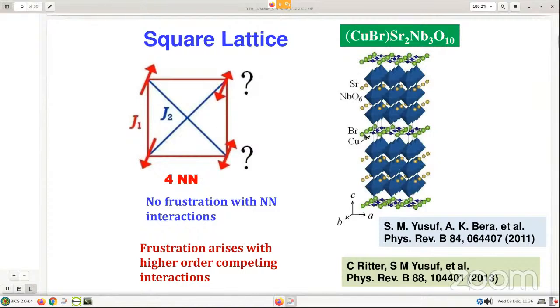So as far as magnetism is concerned, it is the copper spin up, and these copper planes are well separated. Here bromine is green and blue is the copper, so these 2D layers can be treated as a 2D system, because these copper layers are magnetically almost not coupled, because of the large separation. And we have worked on this kind of system.